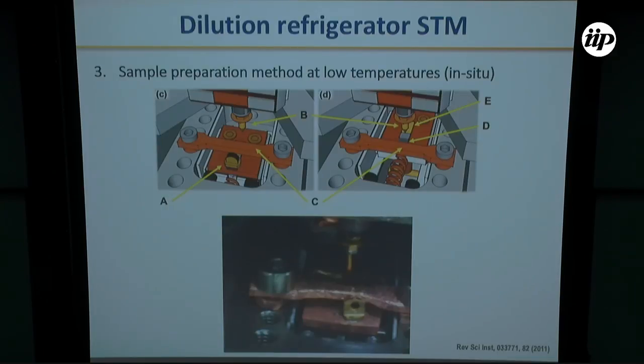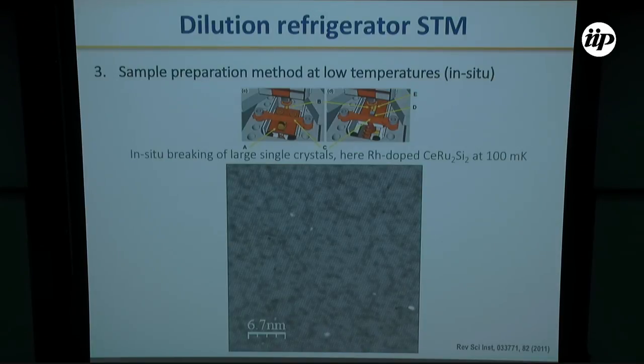We use this mechanism to cleave the sample, producing very flat and large atomically flat surfaces. And here I show you an example of one of the surfaces produced after this cleaving at 100 millikelvin. But we have already used this method to cleave many systems, many crystals.